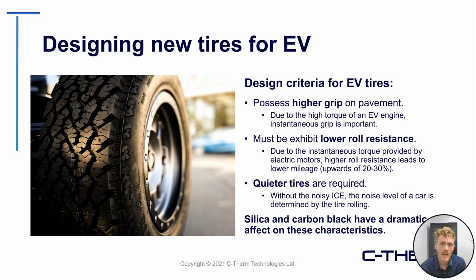So one of the more interesting components is that a lot of the electric vehicles on the market today have specific tires that are formulated to have a very low rolling resistance. Because typically if you use regular tires on these systems, you have a decrease in mileage of around 20 to 30%, which is pretty detrimental with these emerging technologies.